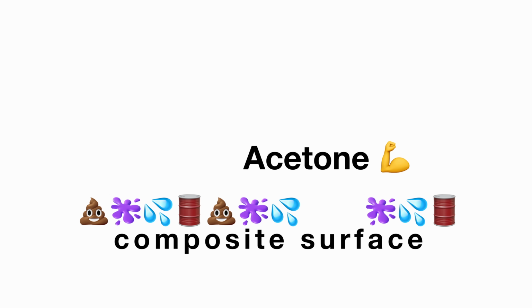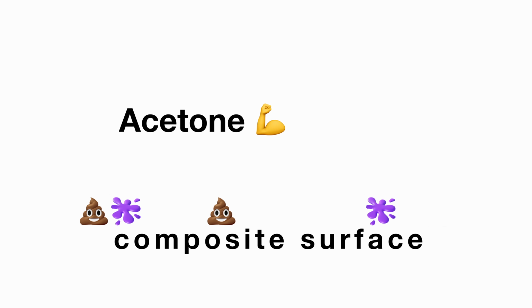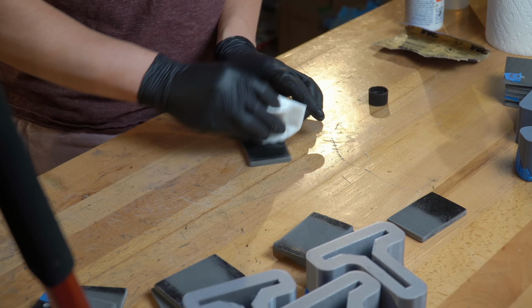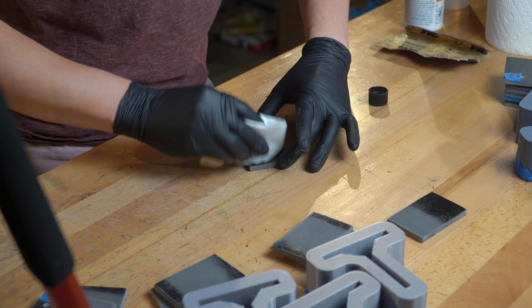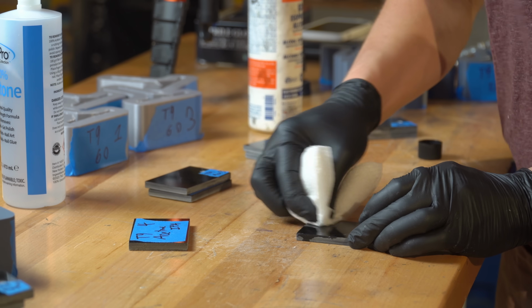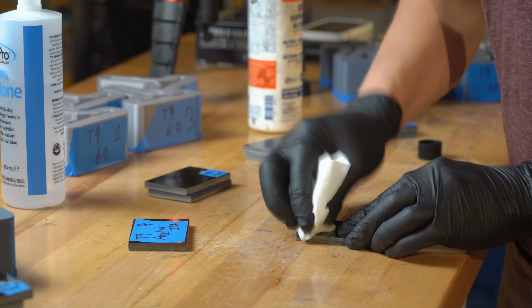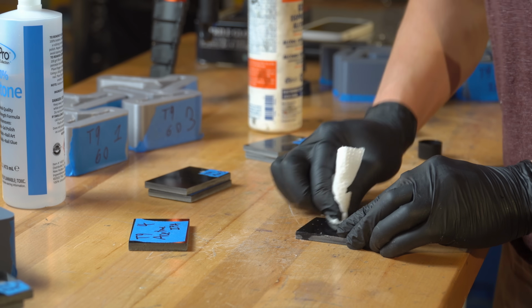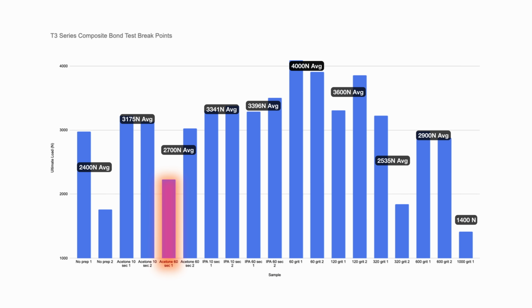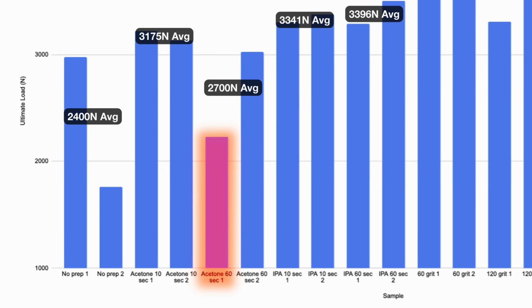The theory here is that as the stronger solvent, acetone will eat away more of the surface contamination than IPA. It also slightly dissolves the top layer of resin in the composite, which is good in moderation. That helps open up some bond sites in both pieces, but it can also degrade the top layer of each composite, so the acetone should only be used in short durations, which is why I'm limiting that wipe to 10 seconds. If the acetone pools on top for longer than 3 to 5 seconds after wiping, you'll start to damage that top layer of resin, and this is likely the cause of some of the low results with long acetone wipes I did in earlier tests.